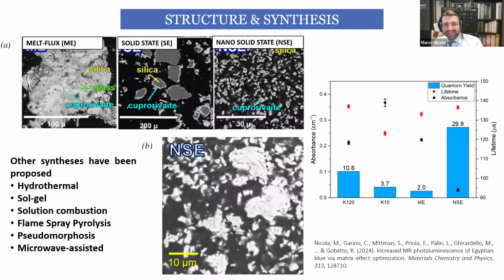Anyway, the way I produce Egyptian blue can deeply change its nature, its luminescence, its features. For instance, here we can compare the production of Egyptian blue made with two different techniques. One is melt flux synthesis, that is a traditional method very similar to that used by the Egyptians. And another is solid state synthesis, a method that doesn't involve the use of flux, but needs a higher temperature, not very much higher, like 100 degrees more, so not 900, but 1000 degrees, to produce this kind of Egyptian blue.